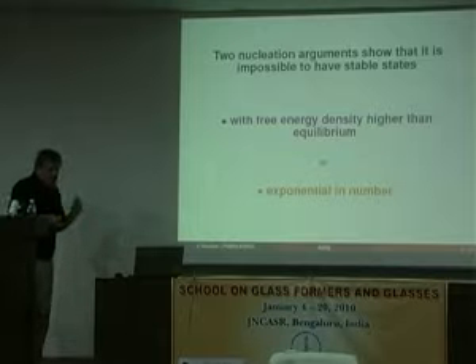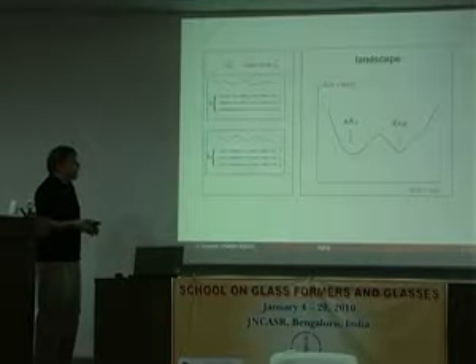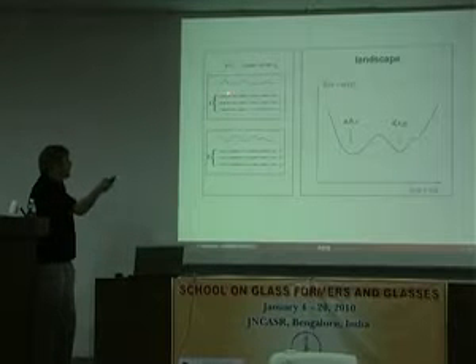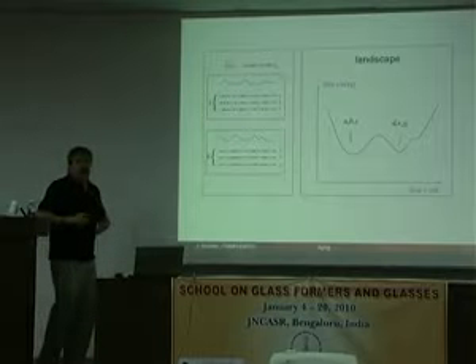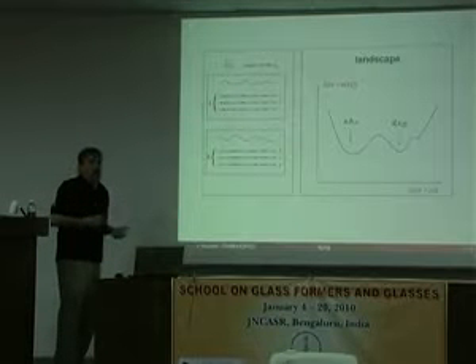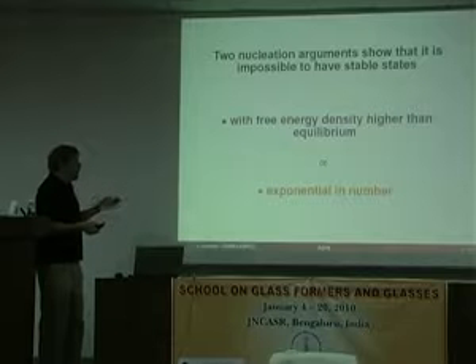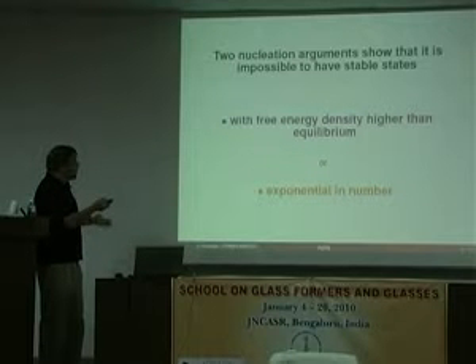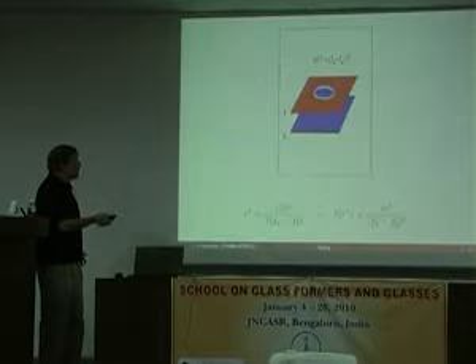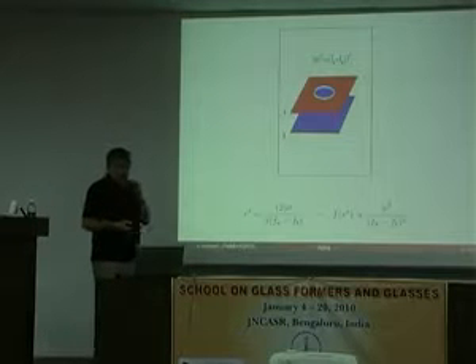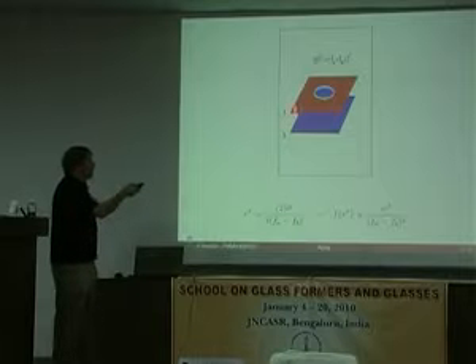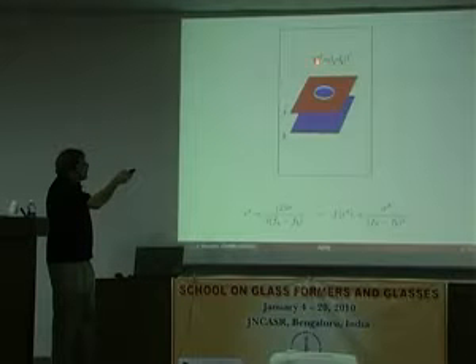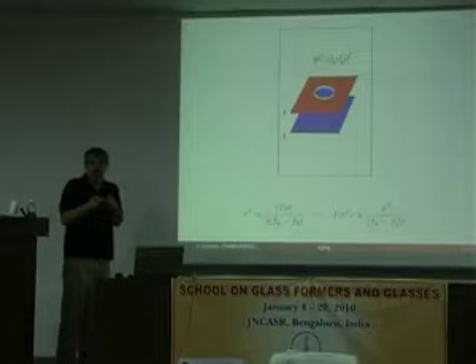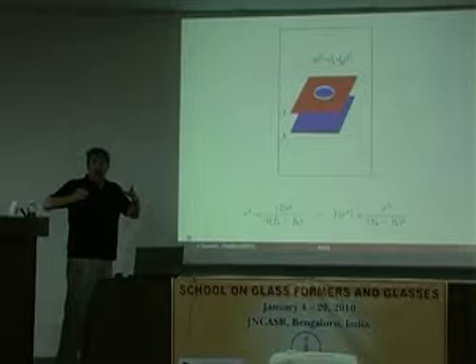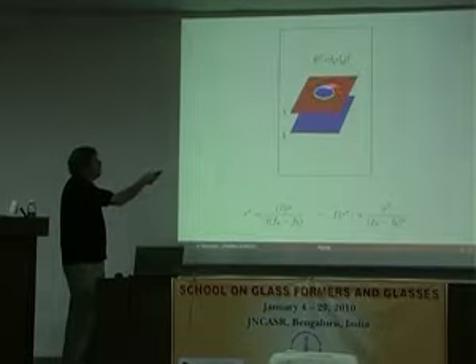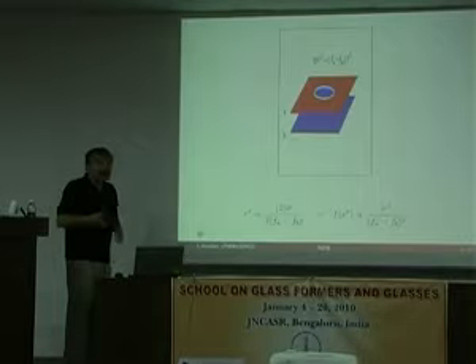So let me go through two nucleation arguments just to convince you that neither this nor this can really be a state which lasts forever if they have higher free energy. We already gave this example the other day. I'm going to also give this one. So the first argument was the nucleation argument. If you really have a metastable phase, you can easily calculate how much it costs to nucleate a bubble. The highest price you can calculate, taking into account that you pay at the boundary and you gain in the inside.